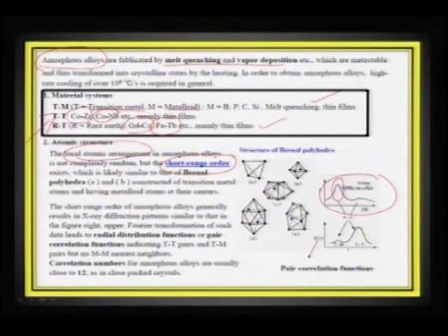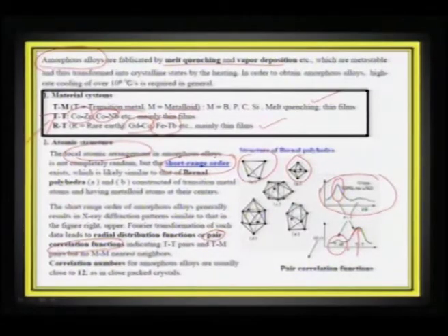So if you actually look at the pair correlation functions for such amorphous alloys, you would find a response for the transition metalloids, or for alloys, which gives an indication that the pair correlation functions indicate small polyhedra, of the order of say 4 to 12. They constitute a short range order. As a result, you can get very different magnetic phenomena compared to crystalline materials.